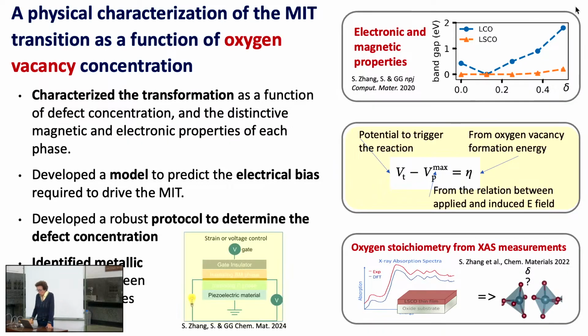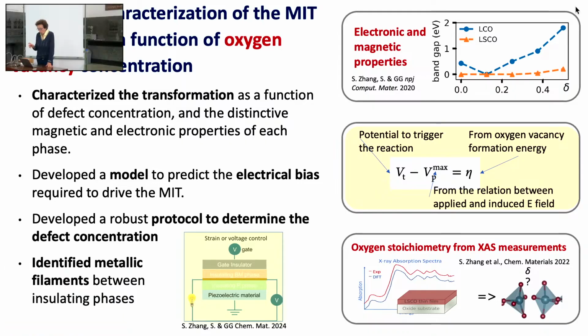And so one thing that I should mention is that for these materials, the level of theory that we are able to use is much lower than the level of theory that I showed you before. And this is because, for the expert, it's DFT plus U. And there is a parameter that we fix by doing something that is not quite good. I mean, it's good, but you cannot really completely call it first principles. We fix it a little bit by comparing with experiment. So we have a long way to go, but from what we did to understand the transformation and the defect concentration, we understood how the material works. To be accurate, a long, long way to go.